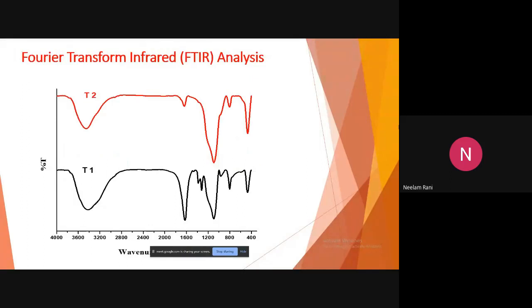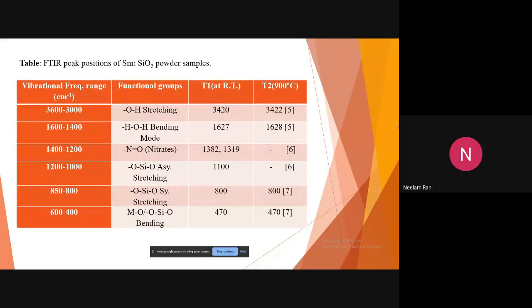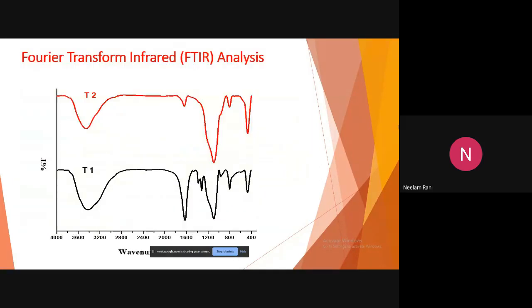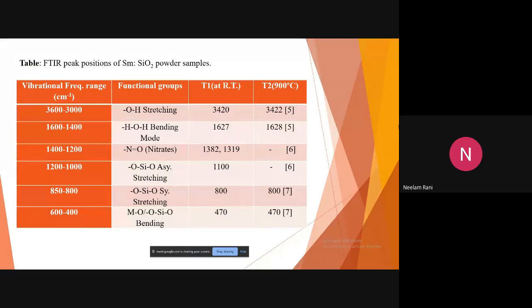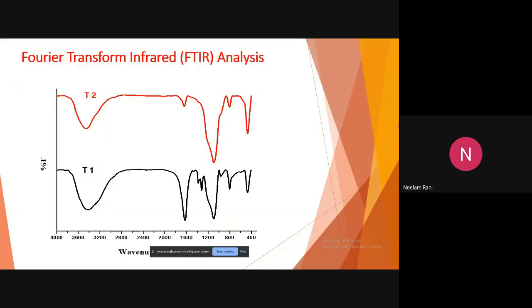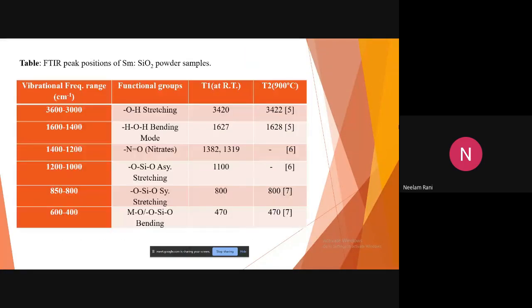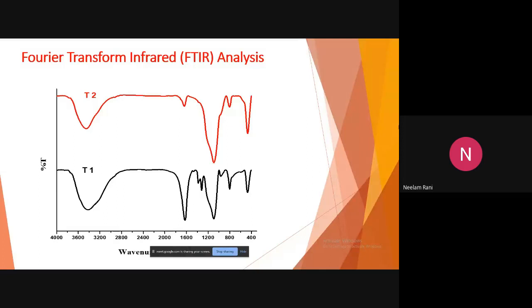This is the FTIR analysis of the sample, T1 for the as-prepared sample and T2 for the annealed sample. These are the peak positions of samarium silica powder samples. As you can see in this slide, different vibration frequency ranges correspond to different functional groups from starting to end point. The main one is metal oxygen bonding, that is samarium oxygen bonding, near 470. This is called the fingerprint region, which is different for every material, and the intensity of the peaks increases with increase in temperature.